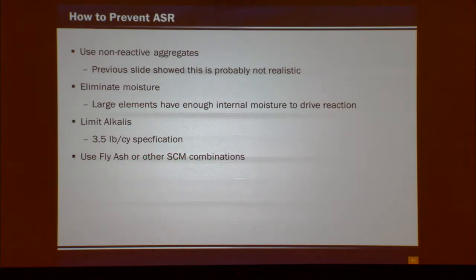And so if you look at our specification, we have 8 mix design options. All those mix design options are there to mitigate ASR. They're there for no other reason other than to mitigate ASR. So if you have a contractor saying, no, I don't want to use one of those options, you're running a risk that you're going to have ASR in your concrete down the road. It may not happen a year, 2 years, 10 years, but it may happen 20, 30 years down the road. We found a pavement down in Laredo that has ASR, and that pavement's 25 years old. And it cracked to hell, but it will happen. So be careful with modifying those mix design options.